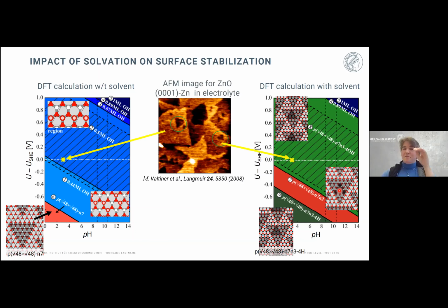Fortunately, we do have some experimental evidence of what we should expect. So this is an AFM image that was taken in the group of Markus Valtiner. And the conditions under which this was taken is marked here by the yellow dot. What you can see is that here we do see definitely such triangular reconstruction, which implies that the diagram we have calculated in the presence of the solvent is representing what is also observed in experiment. So we really need the solvent.